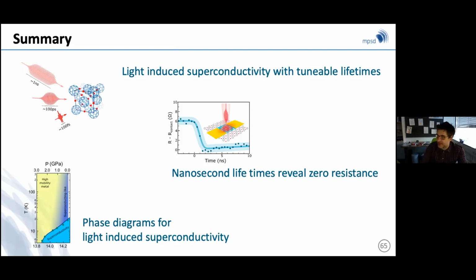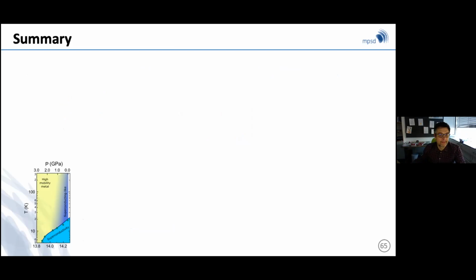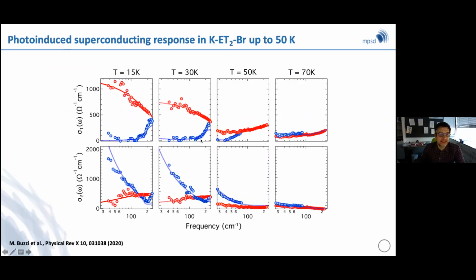But for example, let me actually show you these data. Okay, these are very nice. So this is now light induced in the kappa salts, and what you see is a gap which scales with temperature, by the way. It gets smaller and smaller up to the light-induced TC, let's say, of 50-some Kelvin. In this case, the ground state doesn't even have a gap. So it looks like the symmetry of this light-induced state may even be different than the one you have at equilibrium. This seems like really a textbook s-wave superconductor in which the Tinkham-Ferrell rules hold; it basically looks like mercury, in which all the spectral weight that comes from here goes into the condensate.